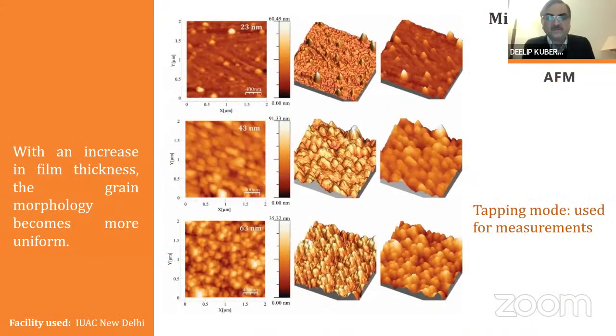And next, after doing the structural understanding of the films, if one goes for what type of grain morphology is there as a function of the film thickness, what changes in the grain morphology take place. So with increase in the film thickness, the grain morphology becomes more and more uniform. And this was done using the AFM facility, which is available at IUAC, New Delhi.